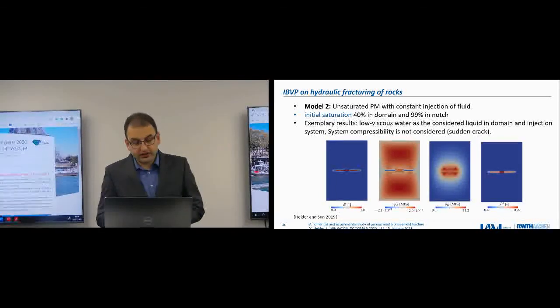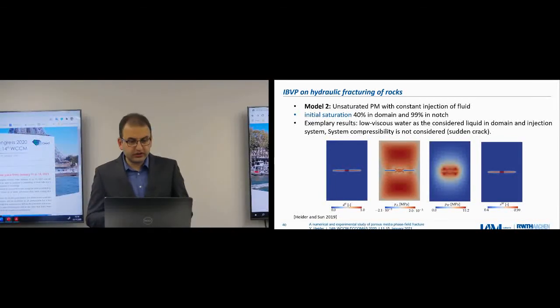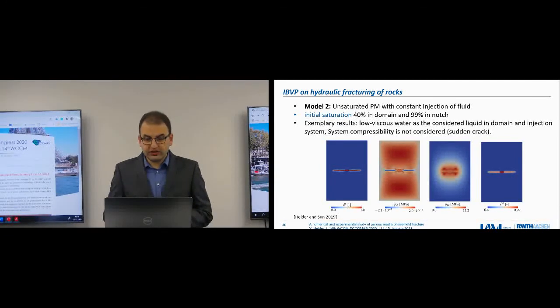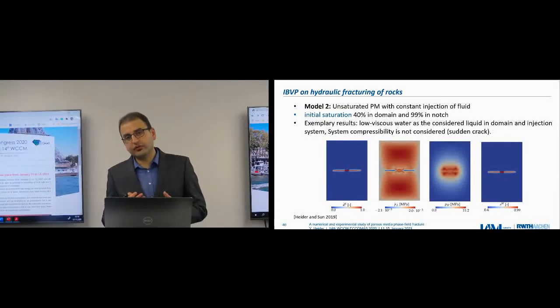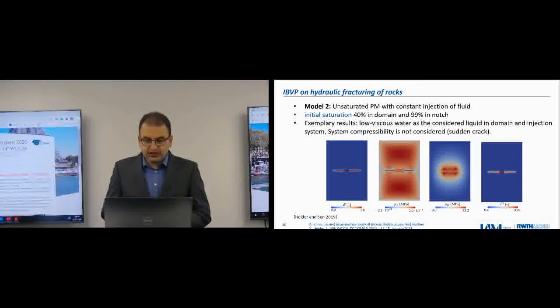The second example is we assume that our material is unsaturated with initial saturation of 40% in the domain and 99% in the notch. And then after the crack, we see that inside the crack we have negative air pressure, which is what we actually expect, because then we have suction towards the crack, and this is what can be observed in reality. And the fluid pressure around the crack is higher than inside the crack. This was an interesting finding. And of course, the degree of saturation inside the crack would be almost 100%. This is logical.